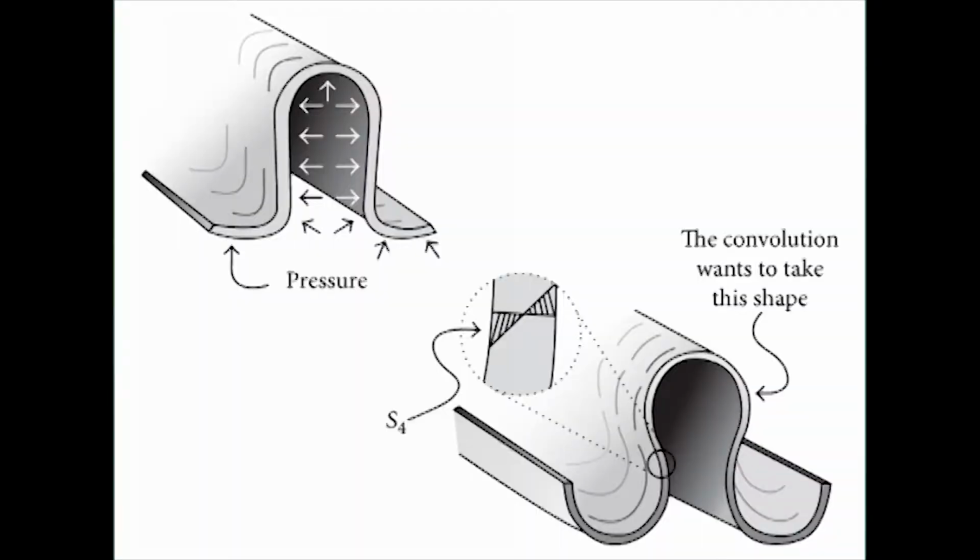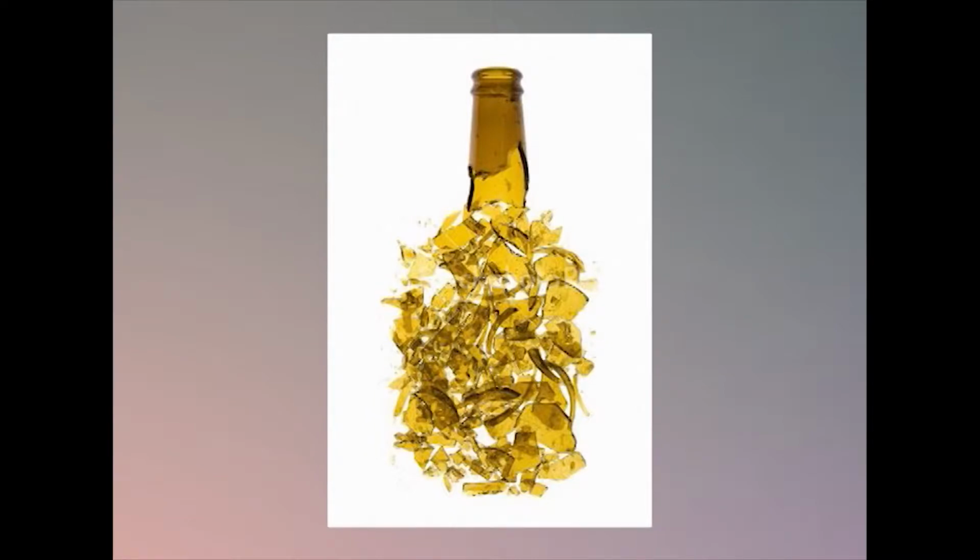If a glass container fractures due to excessive internal pressure, the typical fracture is a straight vertical split in the side wall of the container, which may be due to excessive carbon dioxide in beverages, thermal expansion of liquids due to heat, or generation of gas due to decomposition of contents. It usually originates at the heel or bottom, where stresses are greater. These rarely originate in the neck of the bottle, as the neck is stronger than the side wall.